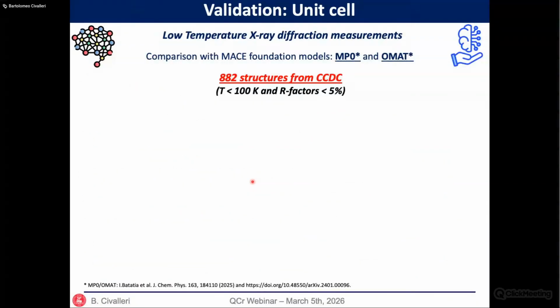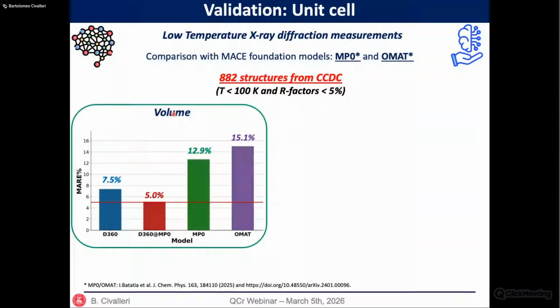So just to make the story short, I would like to show you the validation of this machine learning potential that we try to use to accelerate the prediction of the structure of different MOFs. We refer to low temperature X-ray diffraction measurements taken from the Cambridge Structural Database, up to more or less 900 structures. We compared the results with MP0, a foundation model, and OMAT, two different foundation models for the prediction of material properties. And here are the results for the volume, a macroscopic property, if you want. We get very nice results with our trained model, with respect to the other two more universal foundation models.